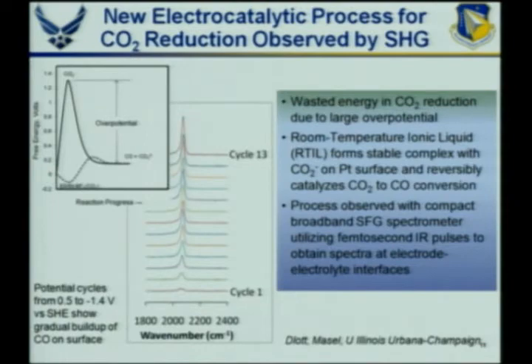So if you look at molecules in the gas phase, many of them are symmetric, but when they sit down on a surface, on an electrode in this case, it removes the symmetry, so this type of spectrometry is sensitive to species on the surface. So they're able to probe and watch this intermediate arise, this complex between the ionic liquid and the CO2 build up, as well as seeing the CO products build up.